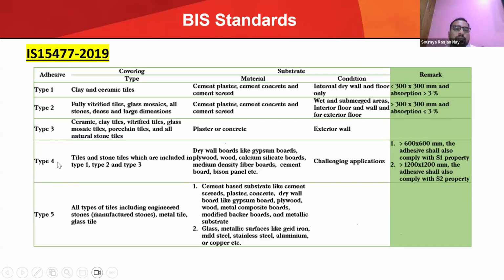Type 1 to type 4 are all cementitious tile adhesives. But type 5 is a resin-based tile adhesive. It's epoxy-based or polyurethane-based tile adhesives. These are reactive tile adhesives. You have to mix two materials, the two components. They will mix and react, and they will act as adhesives, like epoxy and polyurethane.